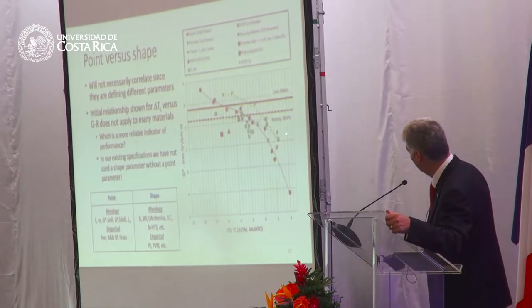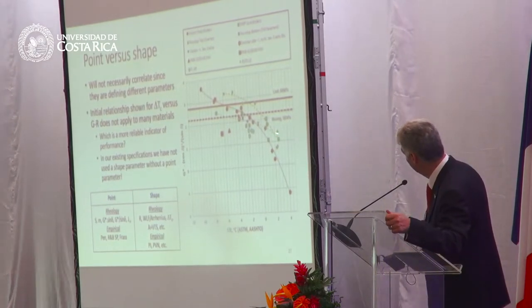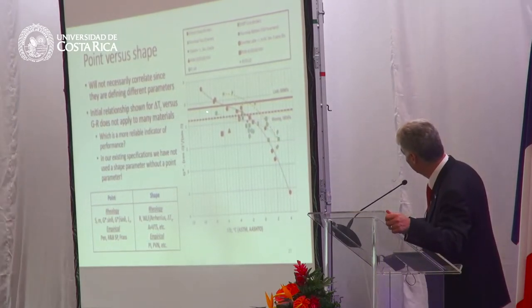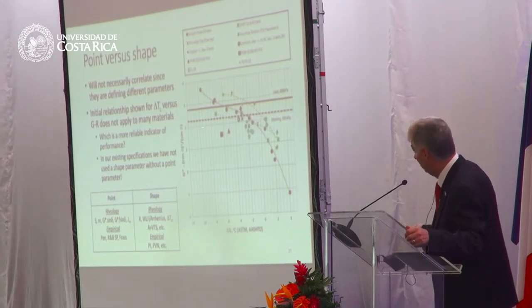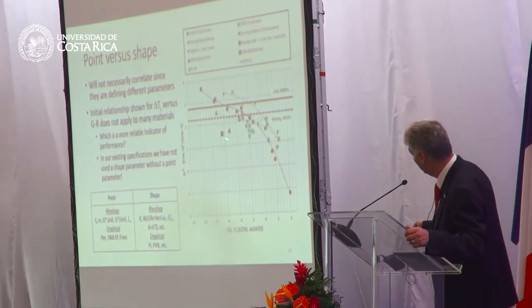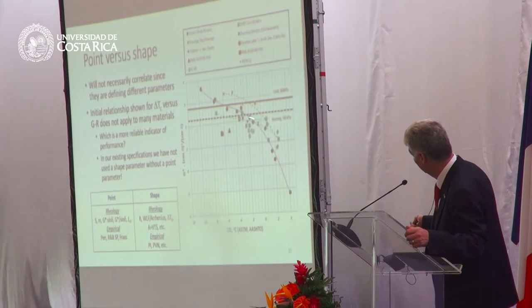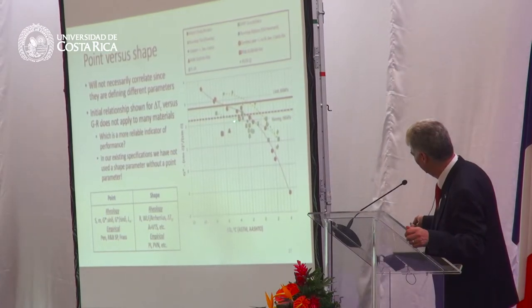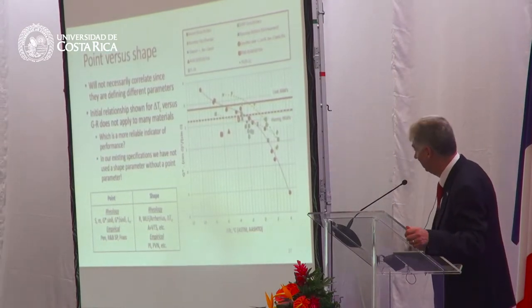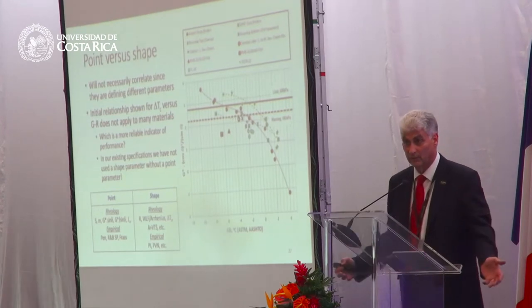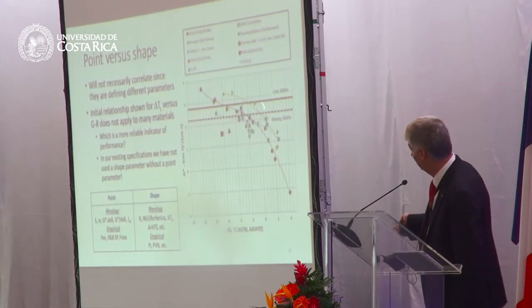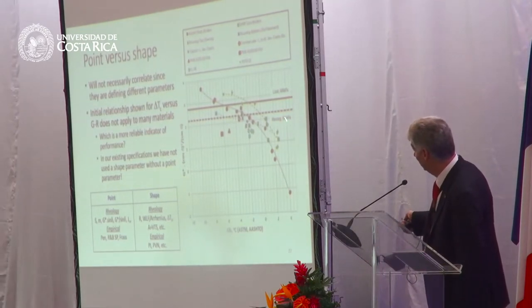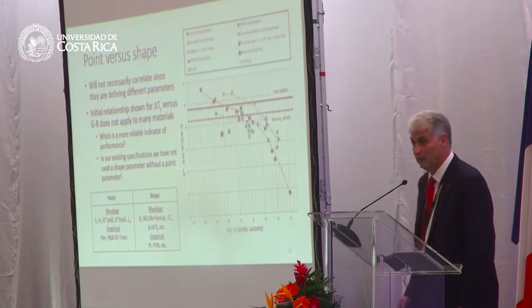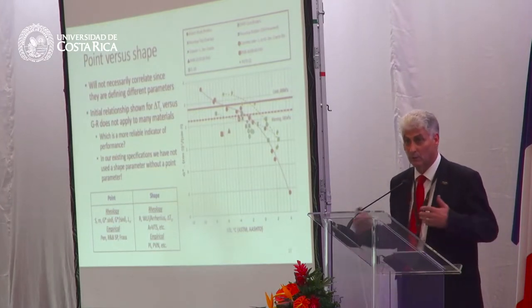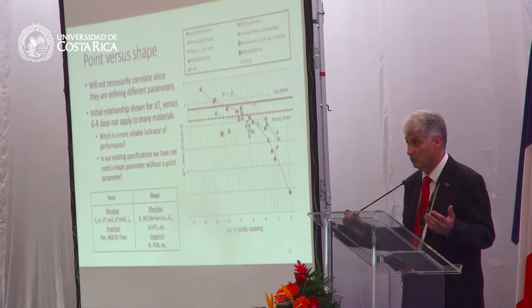But then I plotted the SHRP binders on this. The SHRP binders are a line that moves like this. And then we looked at polymer modified binders. These two are an SBS polymer modified from Russia. This is Florida crumb rubber mixes. And they're all on the underside of the line. If you look at some very complex binders made with very hard asphalt, they're above the line. So all of a sudden we realize, well, this isn't a single relationship.